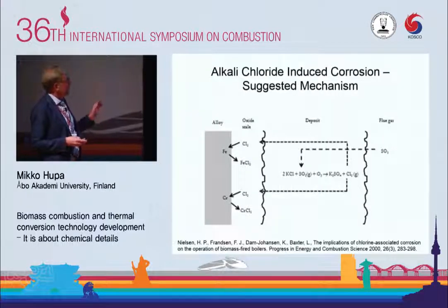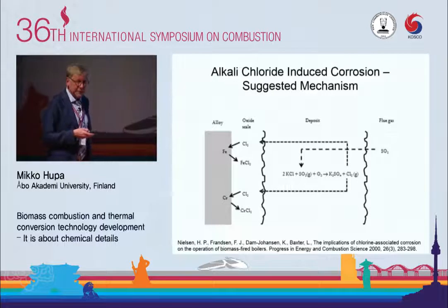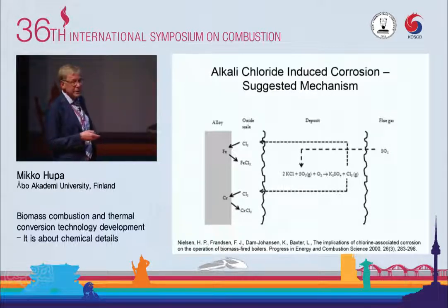But before that, I want to go a little into the mechanism of chloride corrosion because it is interesting. This is a nice concept given by Nielsen et al., and it's quite often referred to. Here would be the steel surface, iron, chromium, and here are the flue gases. And the key is this deposit containing chlorides.